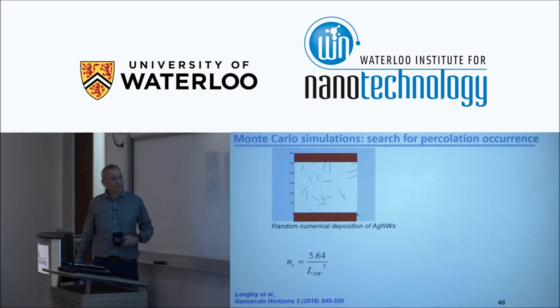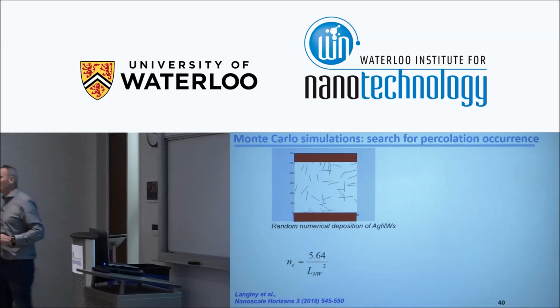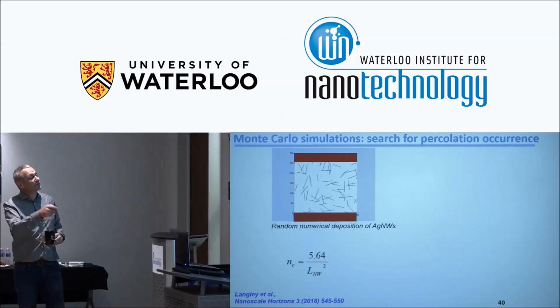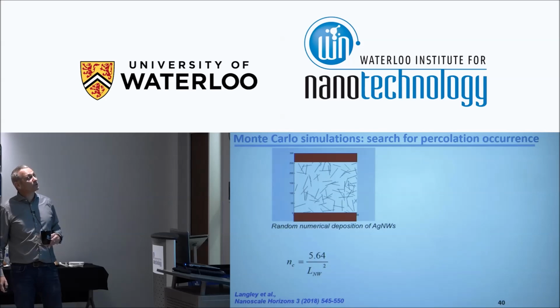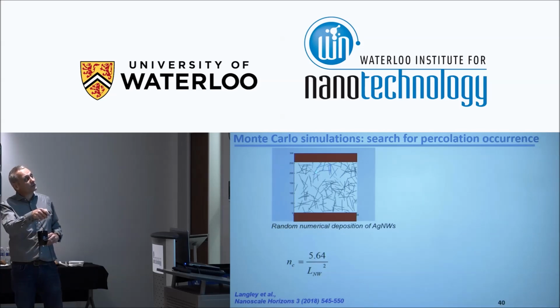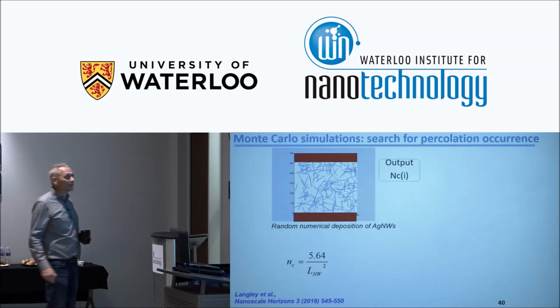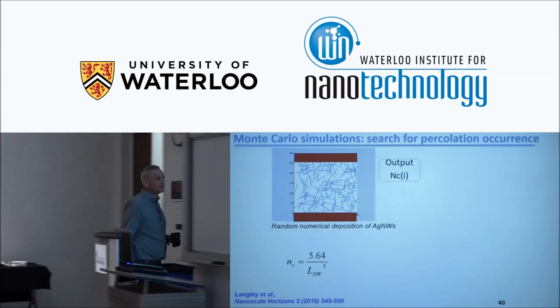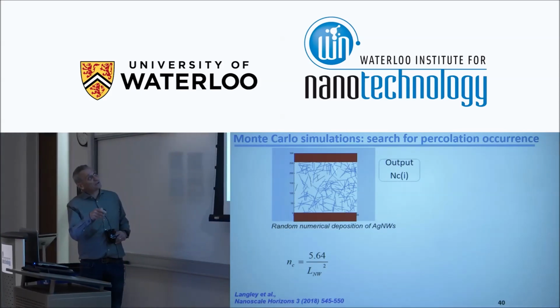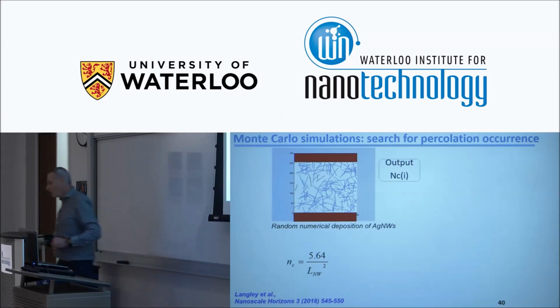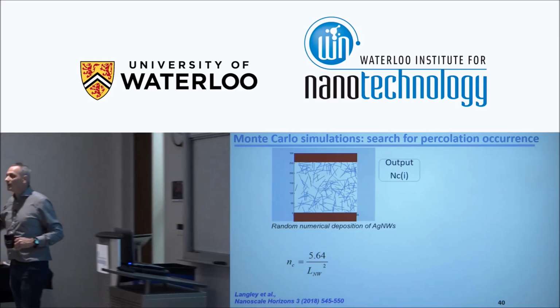For example, we love to use a Monte Carlo simulation. It's not very new. I already saw before that, for example, in 1974, they already used a bit of this. So what we do, we have two electrodes here, and we are throwing numerically some silver nanowires. And when they are forming a cluster, we put them in blue, okay? And we wait to have a percolative cluster through the whole network. And then we stop, and we count the number of nanowires which were sufficient to have percolation between these two opposite electrodes. Okay, we could be lucky or not, so we have to make that again and again and again.